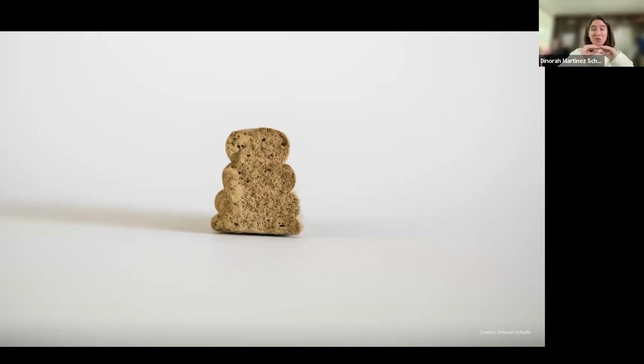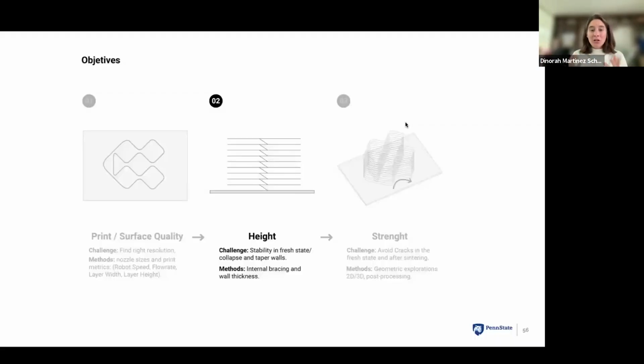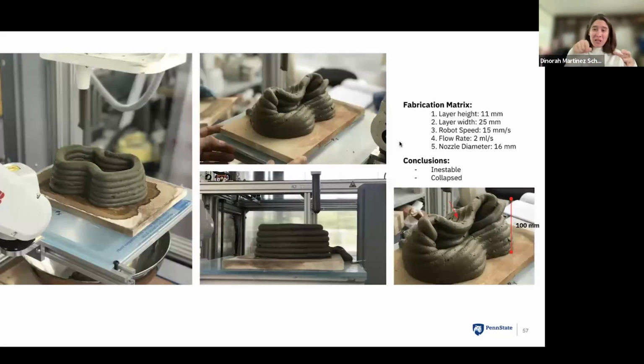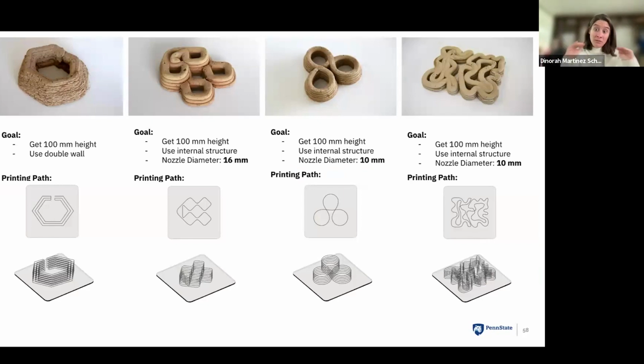The first layers started to be very splashed, and after layer 3, the material started to expand because it's a foam. So I had to start to design with this material condition. The second objective was how can I get the best or better height in the printed bricks? First of all, I started to print only the perimeter, and then I realized I could not get 10 centimeters. That is nothing. So I did different kinds of interior infills to create a better structure in the bricks: double wall, that is the first one, then square geometries, simple infills, and then curvature infills.